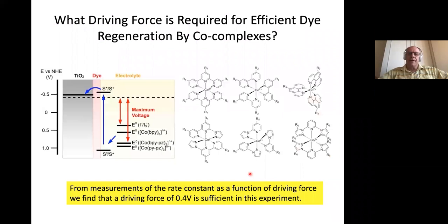So our question now was, if we had 0.7 volts loss with iodide, what do we need in terms of potential driving force to regenerate the dye efficiently? So we could, together with Michael Gretzel and Nasiruddin and the team, synthesize several cobalt complexes with different redox potentials. So here you can see that we can vary the redox potential closer and closer to the potential of the dye. That means that in terms of photovoltage, we can hope that the voltage goes up, because voltage is the difference of this level and this level. So if we go down here, we increase the voltage.